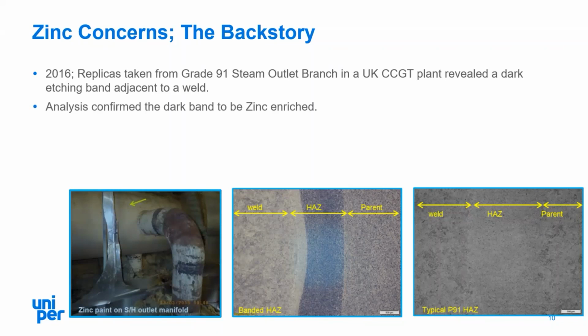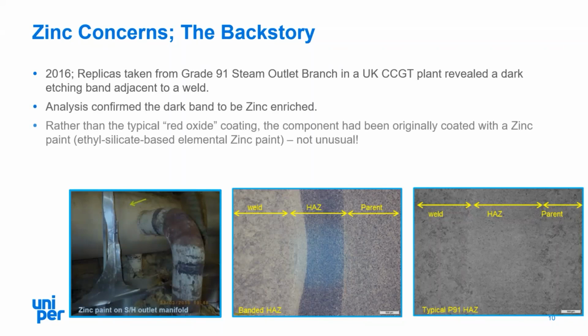Material analysis was undertaken in situ, and this confirmed that the dark band itself was zinc enriched. And when further investigation was done on the background to the component itself, it was found that rather than the typical red oxide coating, which has been long established and tried and tested, the component had originally been coated with a zinc paint, in this specific case an ethyl silicate based elemental zinc paint. But what we've discovered subsequently is this is not unusual, and this is a fairly regular practice which has been undertaken in the last decade or so.